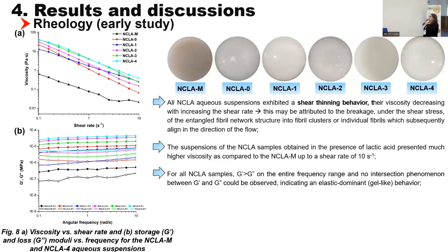We also studied the rheology of the suspension of the nanocellulose fibers that we obtained, and we saw that all the cellulose nanosuspensions present a shear thinning behavior, meaning that their viscosity decreases with increasing the shear rate. This is normal for the suspension of nanocellulose because during the shear stress, the entangled fibril network of cellulose will break and will form cellulose bundles or even individual nanocellulose fibers, which subsequently can align themselves on the direction of the flow and hence the decrease in the viscosity.